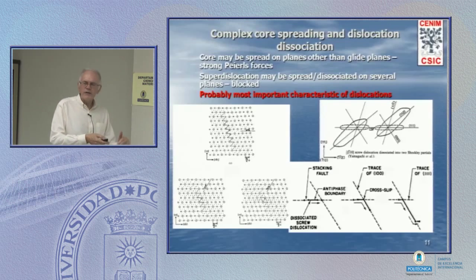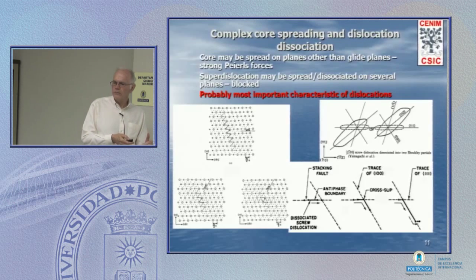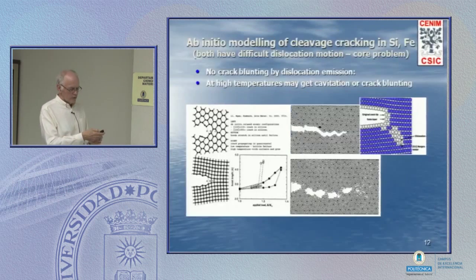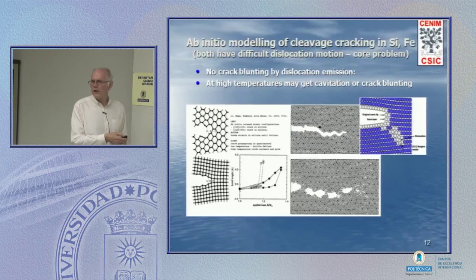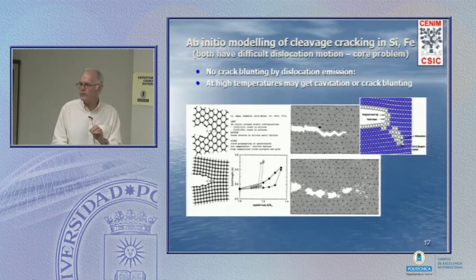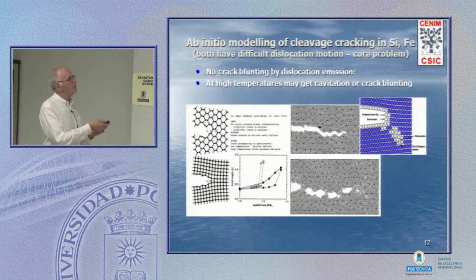So creating the dislocation is more difficult because of the larger Burgers vector, and moving it, because of this core, this is the Peierls stress, moving it is more difficult. Now if creating and moving is difficult, the good news is that I've got a stronger material. Now the bad news is that, as a ceramic, the core makes it difficult to move a dislocation, and I may become brittle because of cleavage cracking.